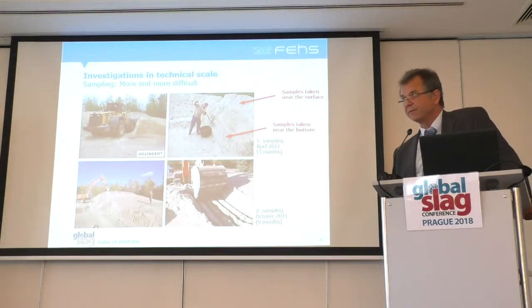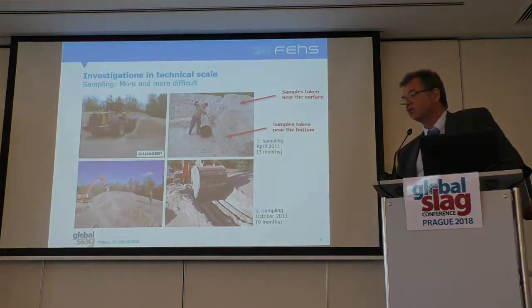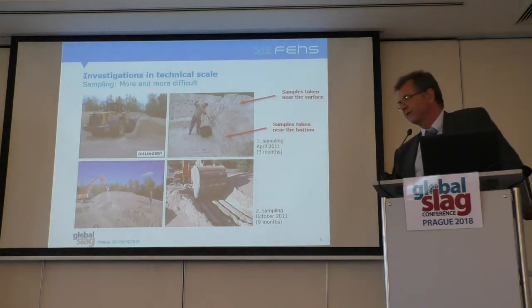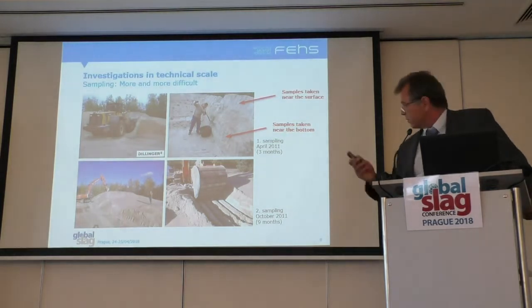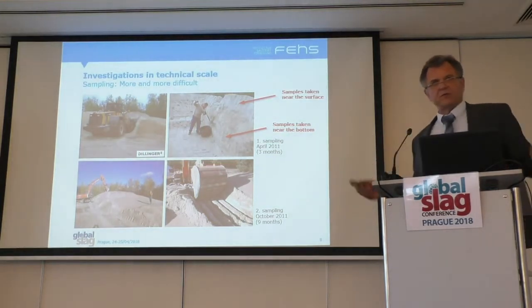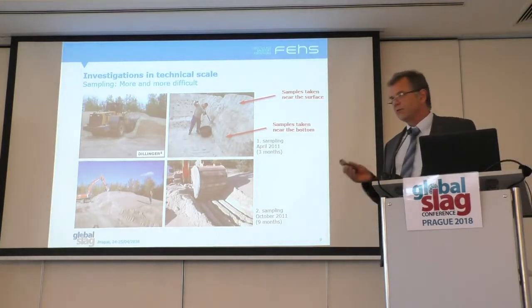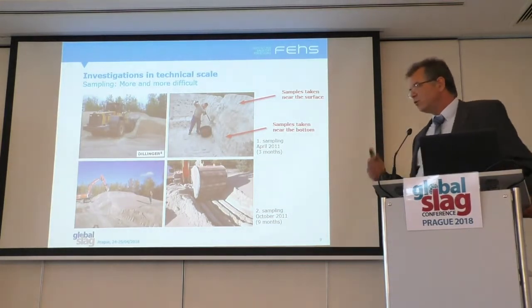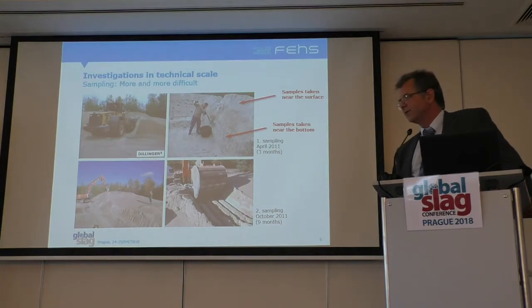That's the only thing. If you have a big storage, which we had in the past sometimes in steel plants, you have not 3,000 tons, but much more and much higher stockpiles. Therefore, the pressure inside the stockpiles will be higher than if you would add only 3,000 tons on a small hill. So it's only to simulate a little bit the real conditions in big stockpiles.